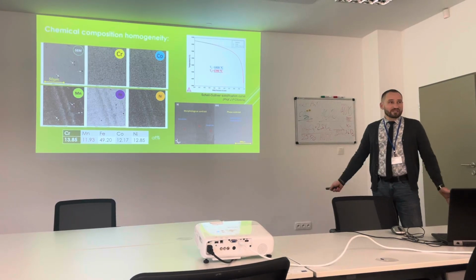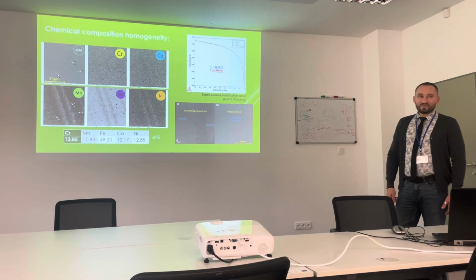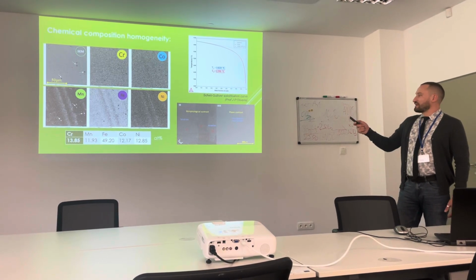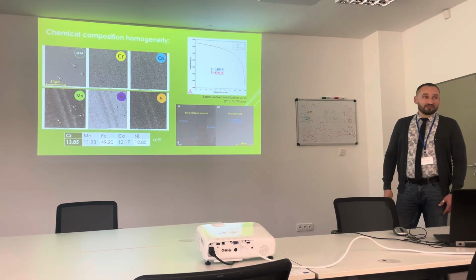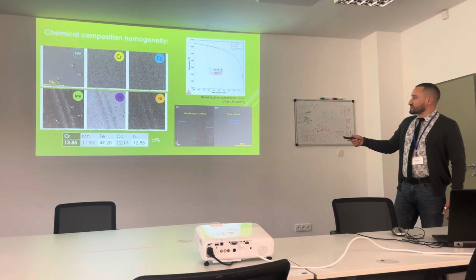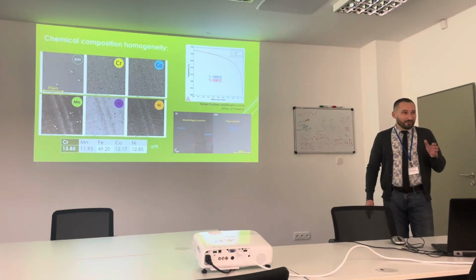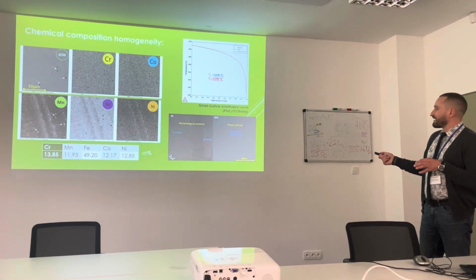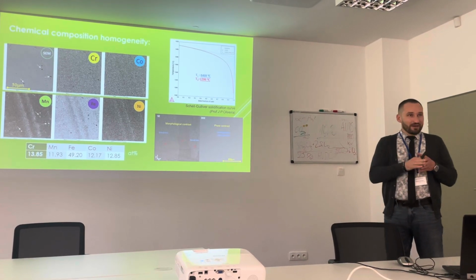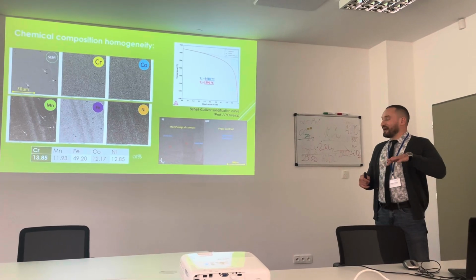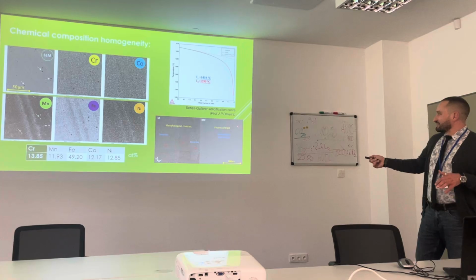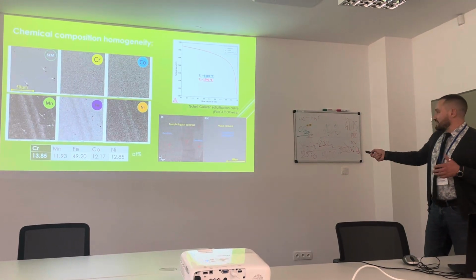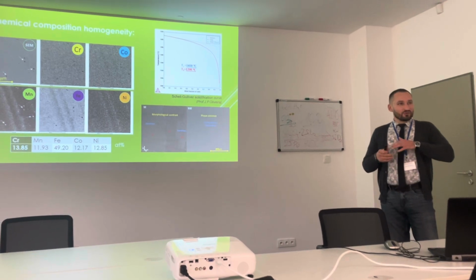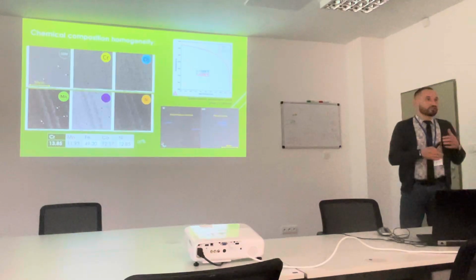The first step of the characterization, in our case obviously, was scanning electron microscopy with characterization of chemical composition. We found out that we have obtained high entropy alloy composition with uniform distribution of each chemical element, and obviously these are micrographs. Secondary electrons reflect the grain boundaries and peculiarities inside the grains, and the backscattered electron mode shows phase composition. We see that we have different grains, and in backscattered electrons we have no contrast. It means that this is a uniform one phase. But yes, this is not clear evidence that we have a one-phase composition.